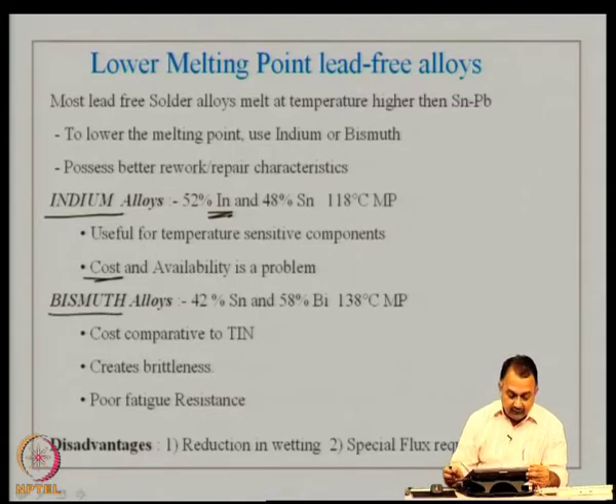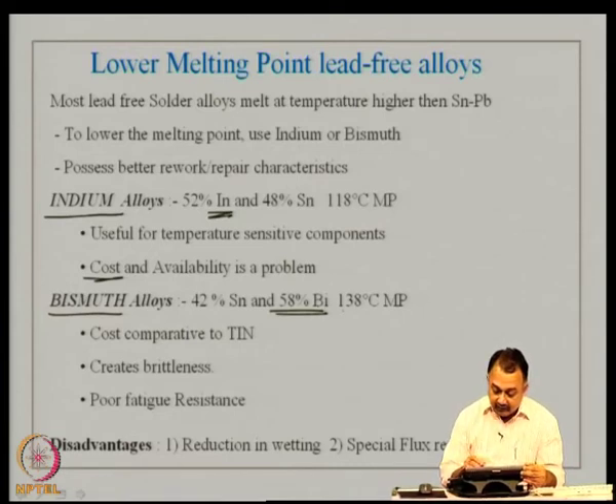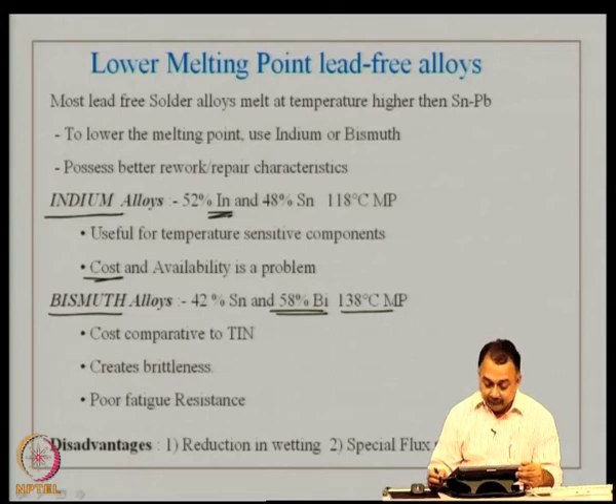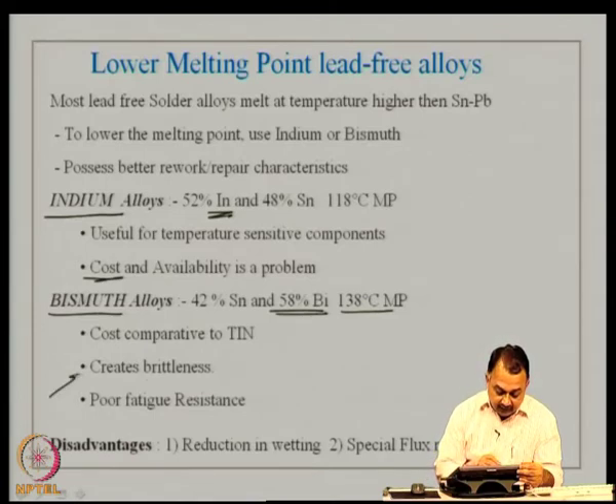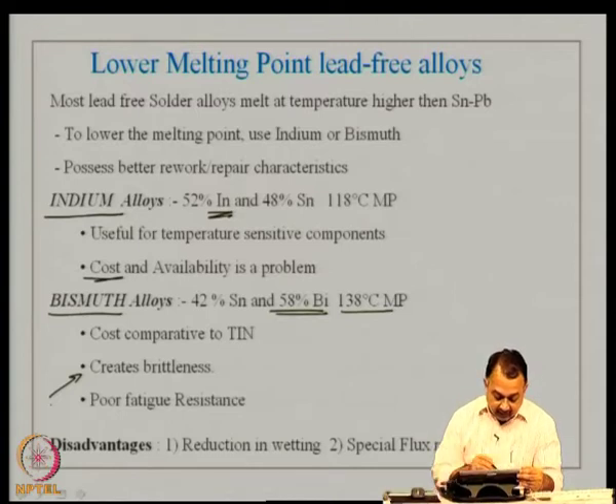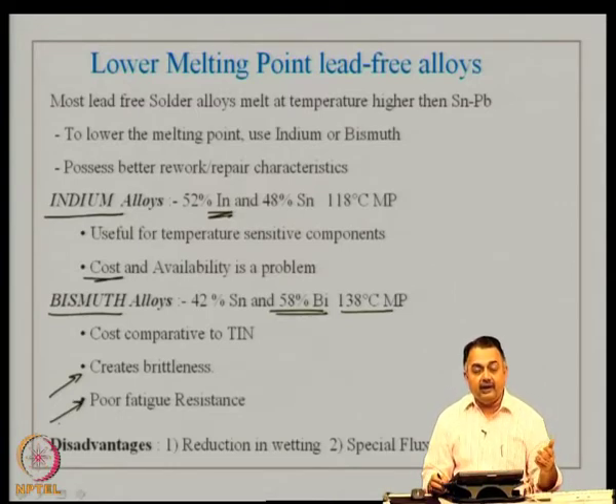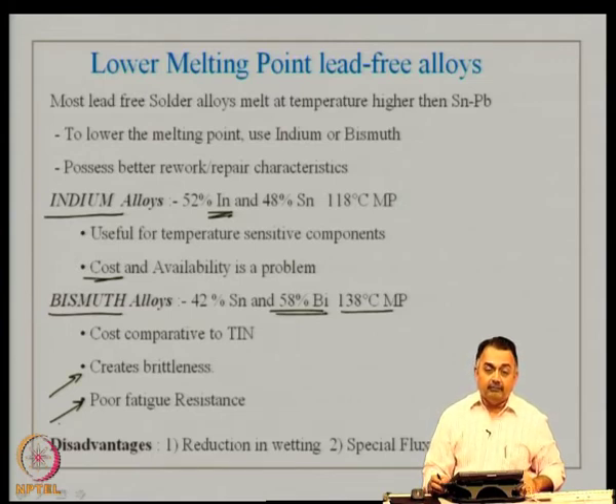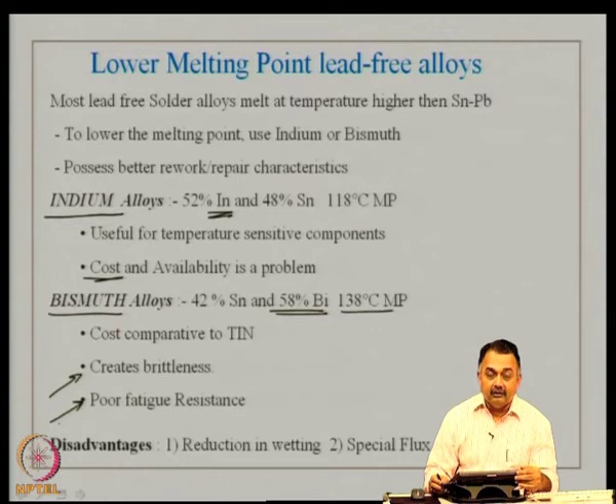Now, the next alternative is using bismuth, where you use bismuth to the extent of 58% and the rest 42% is tin. Here the melting point is 138 degrees centigrade. A very convenient temperature profiling can be done for components that are susceptible to thermal shock. Cost is comparative to tin, and the problem here is it creates brittleness in the solder joint after reflow soldering process, and it also has a poor fatigue resistance. So, on the one hand you are looking at lowering the temperatures, but on the other hand you have problems with the solder joint reliability issues.